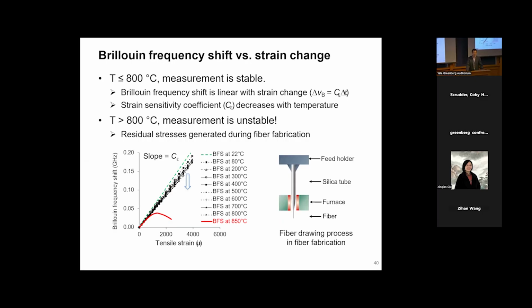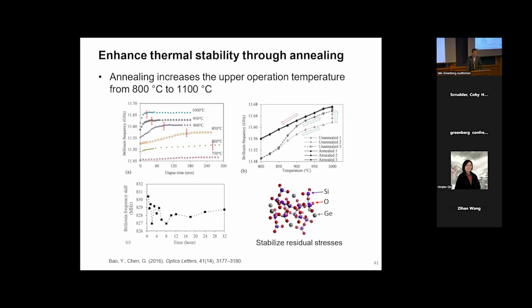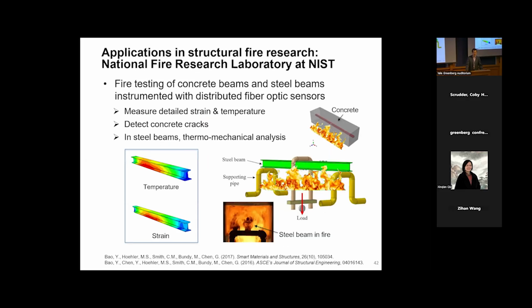We found that when the temperature was not higher than 800 degrees Celsius, the measurement was okay based on our thermomechanical analysis, and we get accurate measurements. But when the temperature was higher than 800, the measurement became unstable. This is because of the material properties, because the fused silica will have some chemical reactions at high temperature. Then we developed a thermal annealing treatment method, and we increased the measurement temperature from 800 to 1100. So this is good for fire applications.